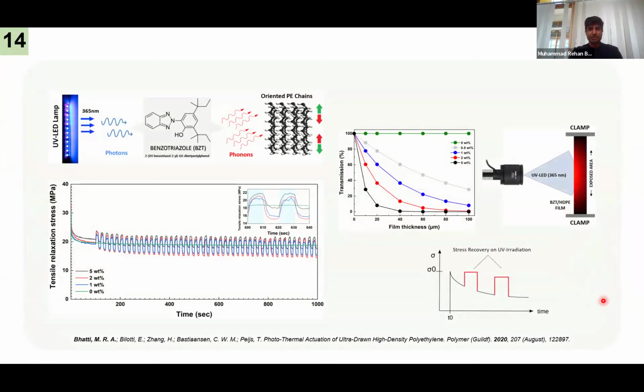The first attempt, we used high-density polyethylene as a substrate using BZT within it. And this is a low-cost, industrially scalable approach towards photoresponsive polymer actuation. In this work, photo actuation of melt-processed ultra-drawn films based on high-density polyethylene incorporating BZT was carried out. And when we illuminated the polymeric films containing BZT at a specific wavelength at which we can get the highest possible absorption of light in the BZT, we get a response in terms of actuation stress.